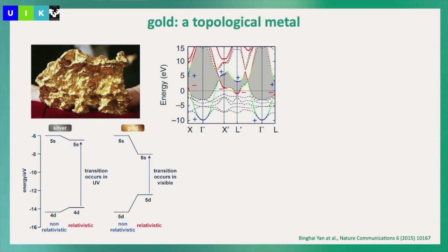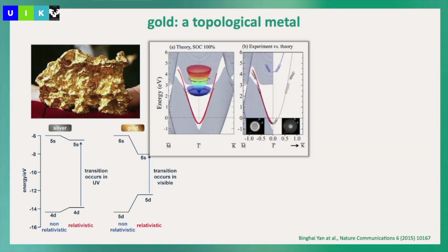So if you calculate here then the Berry curvature, you see that gold is quite good concerning the Berry curvature, but platinum is better. But platinum has many interesting properties which were known before, like it has a very good classical spin Hall effect, you know. It's still one of the best. And all these properties are related to the Berry phase and the Berry curvature, so I think it's interesting.